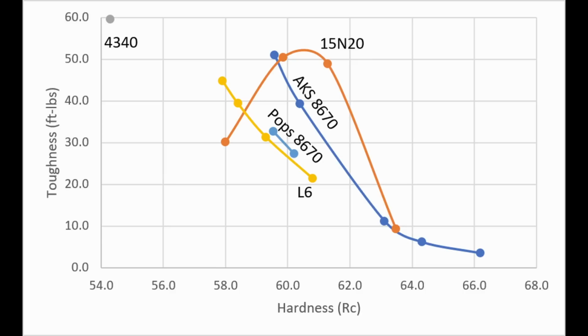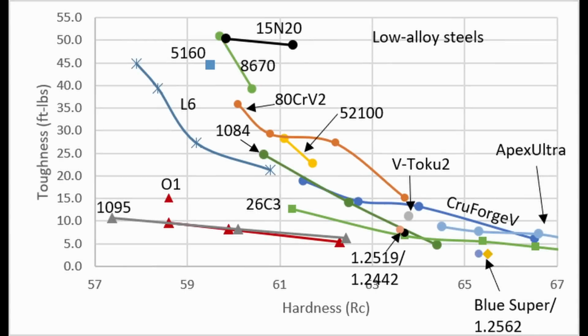And we might say the same thing about the L6. It's very good, not bad, though compared to the 15N20, not as exciting as we might hope. So comparing these steels to others, the 15N20 8670, they are chart topping on my low alloy steel toughness hardness chart. The only steel that really approaches it is 5160, which has lower carbon, 60 points instead of 70 to 75 points of carbon.